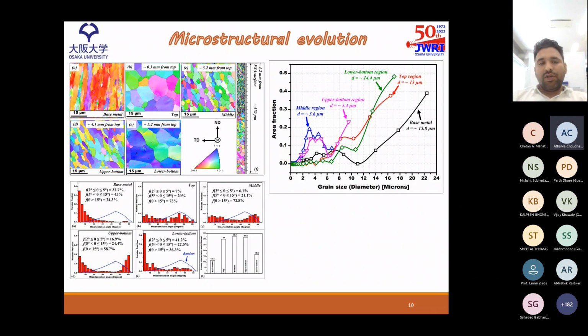Now coming to the microstructural evolution, this is the microstructure of the base material. We can see the elongated grains, which is a typical rolled structure. And this is the microstructure of the top region.